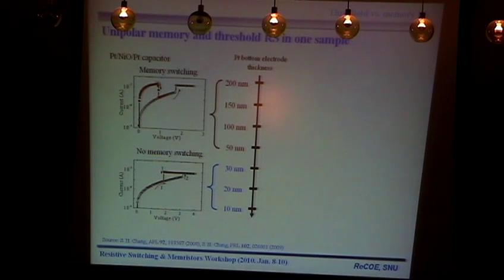The reason we raised this question was that we actually observed a very interesting phenomenon. One of my students made Pt/nickel oxide/Pt capacitors, and in order to change the heat dissipation through the bottom electrode, he changed the thickness of the bottom electrode. With a very thin bottom electrode, where the heat dissipation is very small, he observed non-memory switching, so threshold switching. On the other hand, if we increase the heat dissipation by increasing the bottom electrode thickness, he observed memory switching.